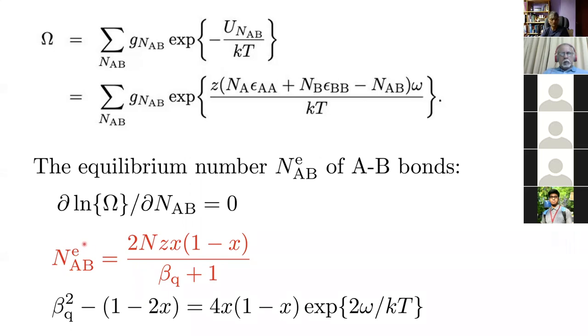All we have to do is differentiate this equation with respect to the number of AB bonds to find the equilibrium number. The result looks like the regular solution model — with coordination number Z, mole fractions x and (1-x) — but includes a special term involving omega that accounts for the finite enthalpy of mixing. Therefore, the equilibrium number of AB pairs is not simply what you'd find in a completely random solution; it depends on omega.